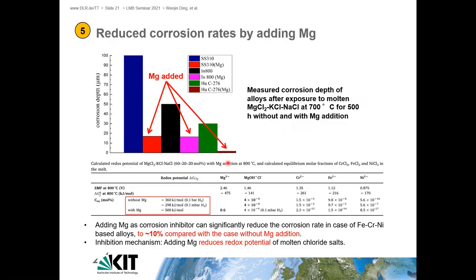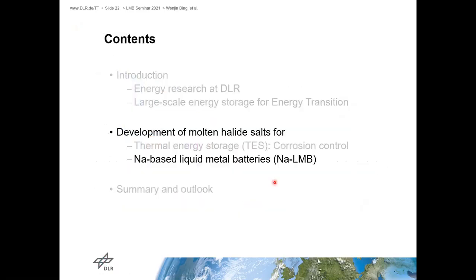And the inhibitor mechanism is, we think, that by adding the magnesium, the redox potential of the molten chloride salt will be reduced to below the chromium corrosion level. So now I go to the sodium-based liquid metal battery, our result.